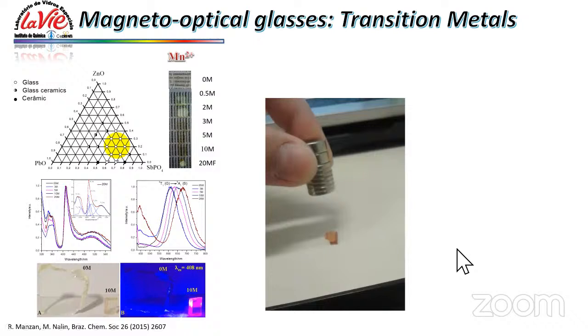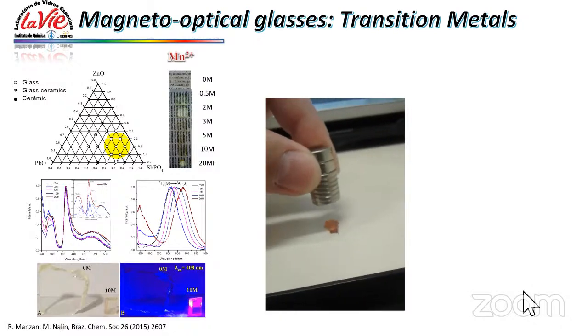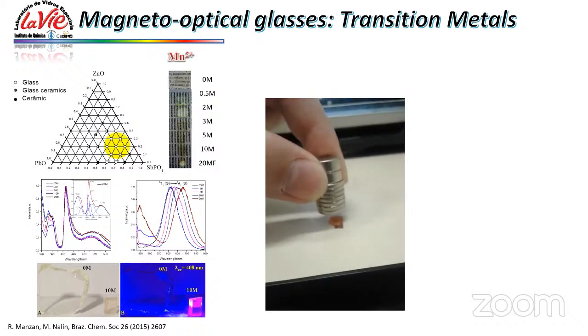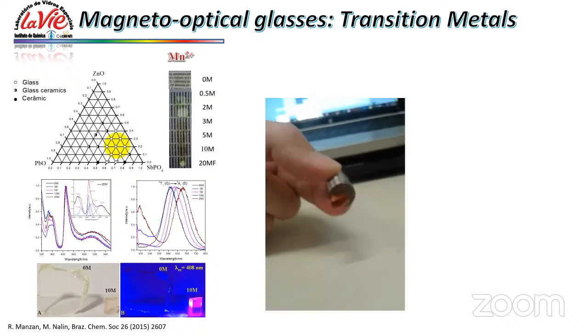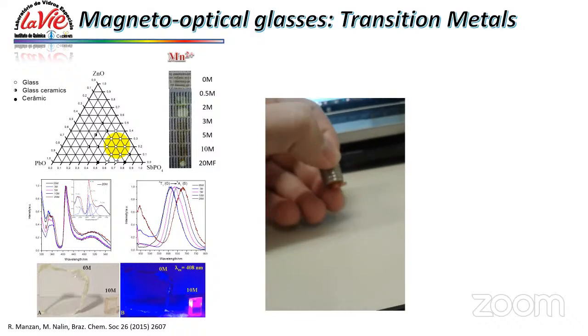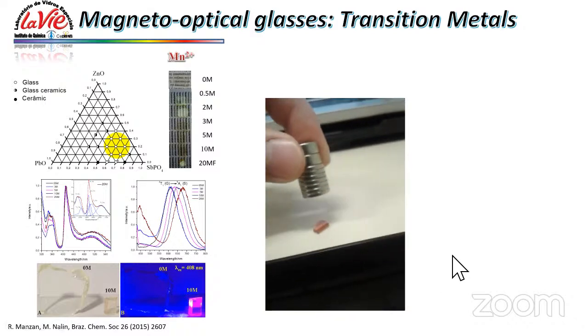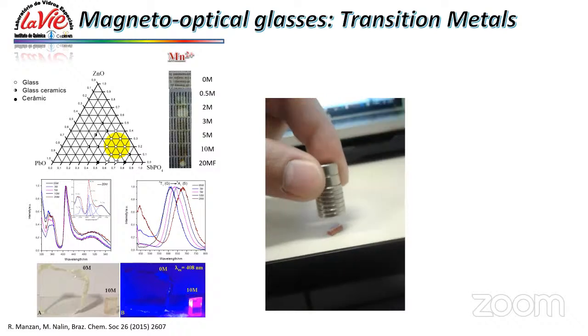So in the beginning, we worked with some compositions. We were intending to use manganese, and we got this kind of samples. They are very luminescent, but the luminescence was not really what we were interested in. So we tried a first approach to really see if this glass was magnetic or not. When we approach a magnet, this is a neodymium-based magnet, to the sample, it is attracted to the magnet. So this was our first really good result.